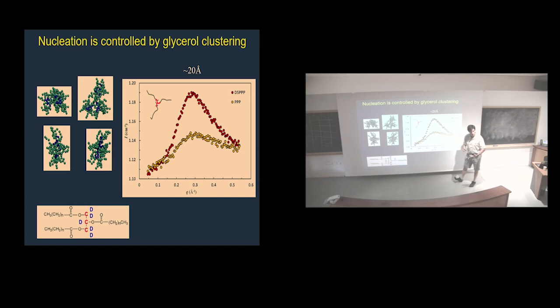You can put deuterium where you want and see what's happening. So look at this. We actually found this very broad scattering from the liquid. Liquid triglycerides scatter in the liquid state. They form structure, they form clusters. It's big, actually, the scattering. It's here, and in X-ray it looks even bigger, I didn't show you.